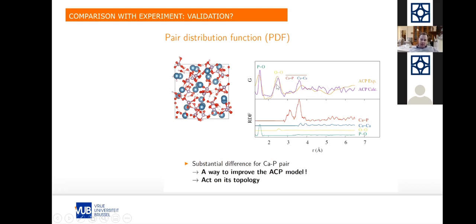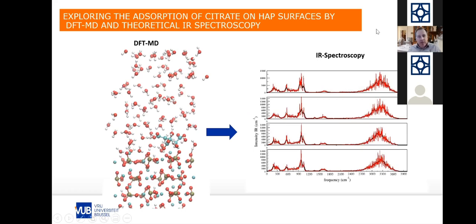So now, if we have this, we can in fact use it to fit an amorphous structure that we have built to the experimental one. So this is very powerful. We can do this with a reverse iterative technique. We did this with reverse Monte Carlo, for example. So we know what we want to have as a result for distances, and we try to calculate the structures with Monte Carlo. So we fit the amorphous structures, the positions of the atoms, to this diagram, the PDF. And this is very important in all the families of materials that we study, this biological mineralization.